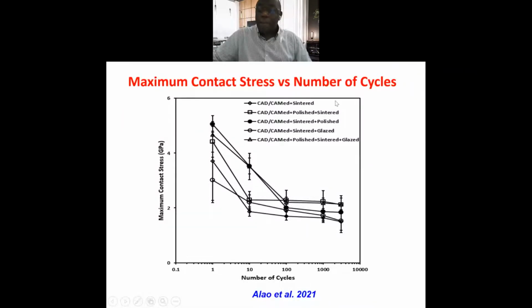So you can see for the proposed process, that is CAD-CAM polished sinter, here we're at 1 cycle, but when the number of cycles increases, you can see it is the only one that survived the 3000 cycles. So that means the fatigue resistance of the proposed process, CAD-CAM polished sintered process, is greater than all other processes due to their rough surfaces. Because the rougher the surface, the heavier the fatigue damage.